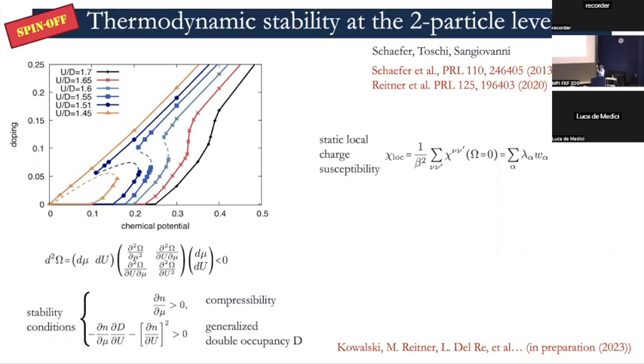So if you look at the static local charge susceptibility that you can calculate directly from dynamical mean field theory, you can express this in a very generic form as a ladder summation of irreducible two-particle vertices. And in this ladder summation, in the end, you always have to sum up the bubbles, and these bubbles end up as a sum over two internal frequencies. Now, if you analyze the quantity which is before the sum, here we're looking at the static local susceptibility, so we have omega equals 0, and you have the two remaining frequencies which are to be summed upon.